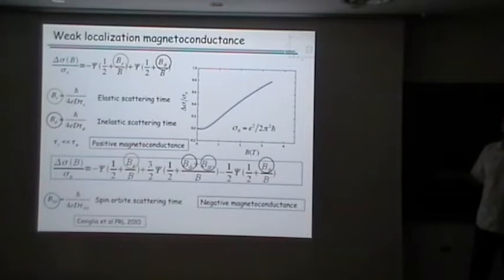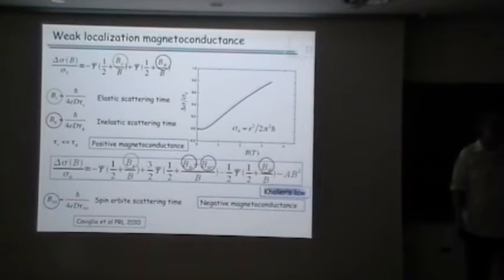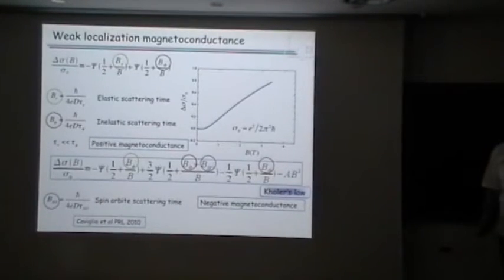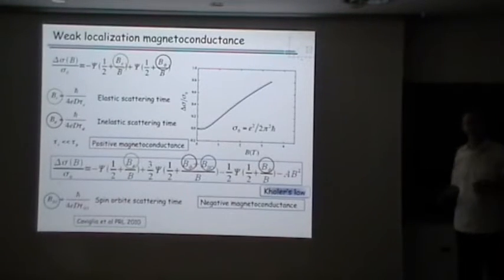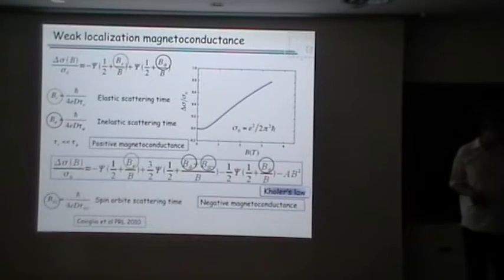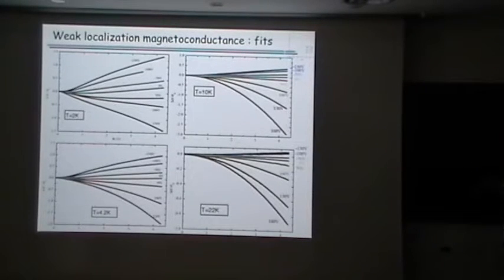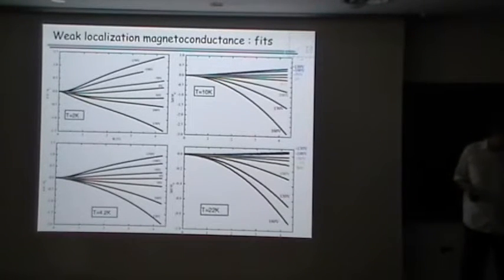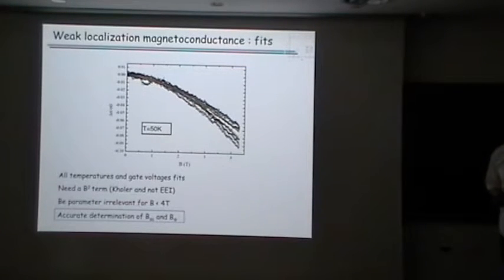It has been done this way in the literature, but I don't think the number you get, for example, for the spin-orbit scattering time is reliable. What we do is add the B-square law we know we have at high temperature. So we have just this A parameter, which takes into account the normal corrections, not the localization one. If you do so, then you are able to fit. These are the data and the fit in color, for all the temperatures and for all the voltages, positive and negative. That means localization is very efficient, provided you don't forget about the Kohler's law. This is the field dependence at high temperature for the Kohler's law itself. So now we have to see what's going on in the system, what is changing so much that the magnetoconductance goes from positive to negative.